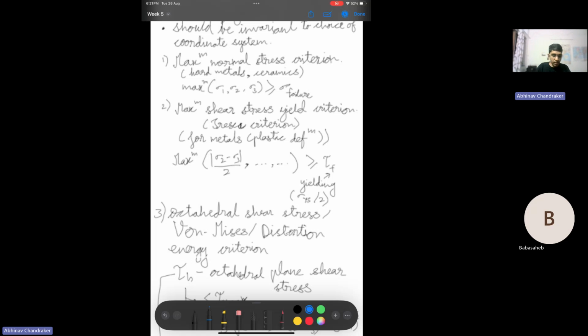So, when we want to compare the stress state of a material in any criterion to something which is more general or easier to compare with, it will be uniaxial loading, because that is the easiest way to experimentally know the property of a material. You just load it in one direction uniaxially. You look at the yield stress and the UTS value, because after UTS the load taking capacity of the material will decrease, so it will naturally fail for the load which has been applied.